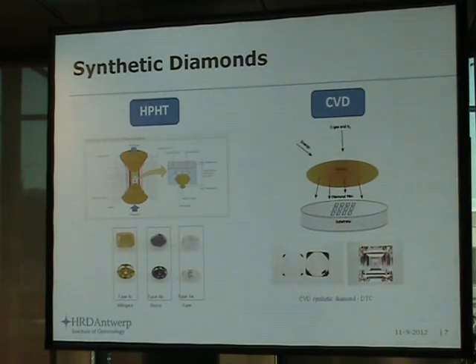Now, the major two methods for producing gem quality diamond at this stage are the high pressure, high temperature treatment method and the chemical vapor deposition. Now, for a long time, this method is well established since the 1950s, and you can see here the as-grown colors of such a method. So what you do with the high pressure, high temperature method is imitating Earth's conditions. So you mimic the high pressure, high temperature formation conditions of diamond. Starting from a small seed crystal, there is a carbon source, and then the building blocks, the carbon atoms, are sedimenting down on that seed crystal in that high pressure, high temperature region where diamond is formed.